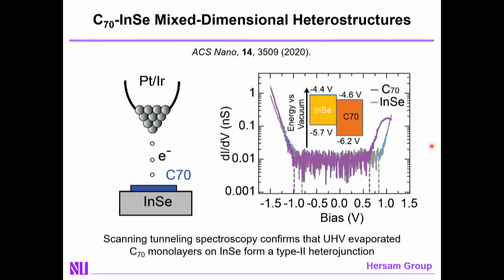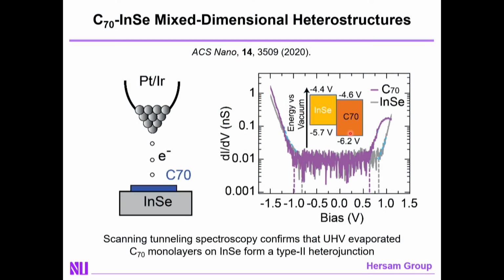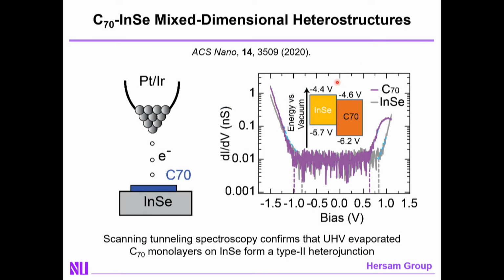Next example I want to give is C70 indium monoselenide. This is a system that I'm introducing because we've changed the orientation energetically of the 2D and 0D component. In this case, we would anticipate electron transfer from the 2D side to the 0D side, whereas in the phthalocyanine MoS2 case, it was the inverse charge transfer. These are formed by evaporating C70 onto indium monoselenide in ultra-high vacuum. The reason we do this in ultra-high vacuum is that indium monoselenide is highly reactive chemically.